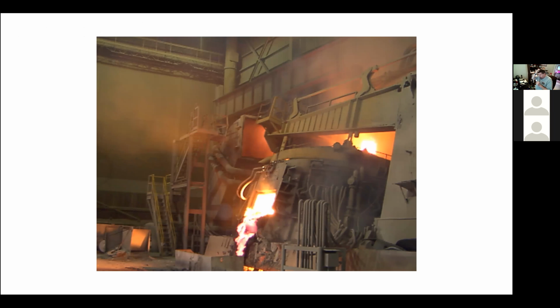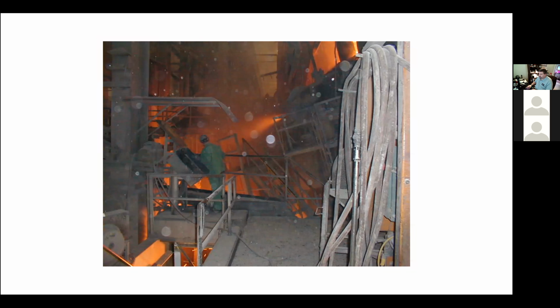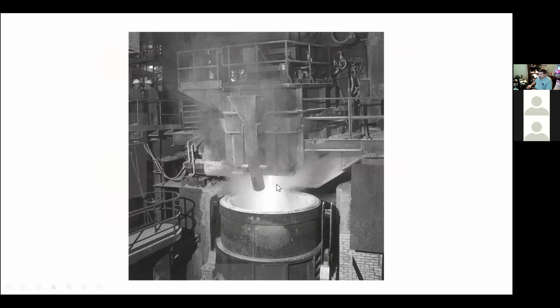And then we might take a temperature, a steel temperature, using a thermocouple probe. And we might also take a sample of the steel and have it tested at the lab. And if we figure, yeah, that's okay to tap and send downstream, well, then we'll tilt the furnace over, and here you can see the front of the furnace. So it's tilting over, and the steel pours out into the refractory lined bucket or ladle.